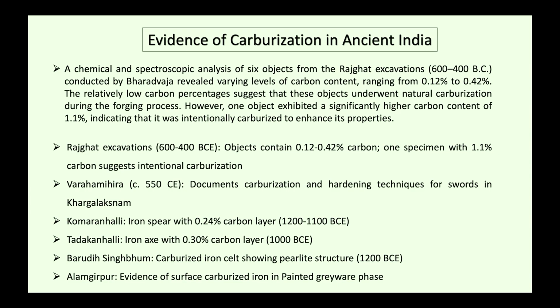In the Rajghat excavation, here is an example of metal tools that underwent the carburization process. Objects from the Rajghat excavation, 600 to 400 BCE, contain 0.12 to 0.42% carbon. One specimen with 1.1% carbon suggests intentional carburization, and Varahamihira in 550 CE documents carburization and hardening techniques for swords in the Khadgalakshanam. And in Komaranhalli, an iron spear with a 0.24% carbon layer, dated 1200 to 1100 BCE.